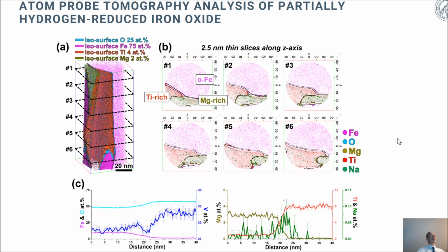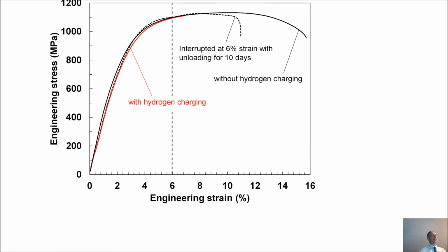So in future, it's also important to not just understand the microstructure, the evolution of fracture, internal damage, and porosity due to the mass loss from the wüstite towards the iron, but also how these impurities affect the rate of the reduction. Last but not least, we should also emphasize that you must understand how much hydrogen really remains inside of the material. Because when we have iron that is produced with too high a hydrogen content, due to this type of reduction, you might later encounter the so-called hydrogen embrittlement in your materials, which you of course do not want.